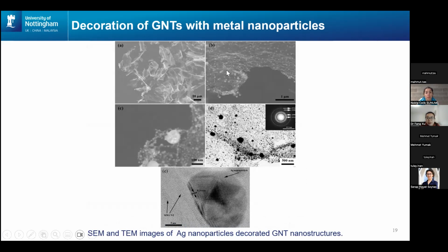Again, lower magnification images show the uniformity of the silver nanoparticles, and C, D, and E are the TEM images. If we look at C, we can see the very tiny silver nanoparticles are coated uniformly on carbon nanotube as well. So compared with copper nanoparticles, silver nanoparticles have a very small size and better coverage on the carbon nanotube. Copper is not as good because it's more difficult to achieve the nano size, the smaller size copper particles, but silver is so much better in this aspect.